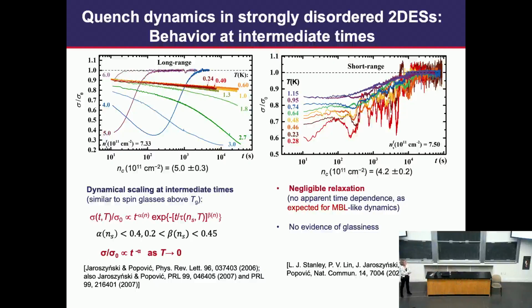Now, even if you don't know anything about what these figures show, you can see qualitatively they look different. First, if you look at intermediate times, apart from the noise, the relaxation is basically negligible. The system doesn't do much, which is what you'd expect in the case of MBL. So we don't see any evidence of glassiness here.